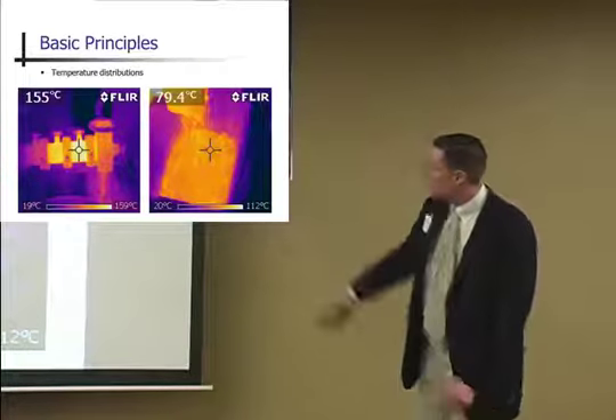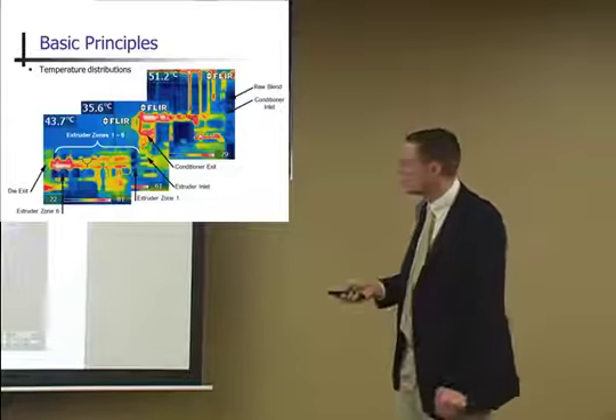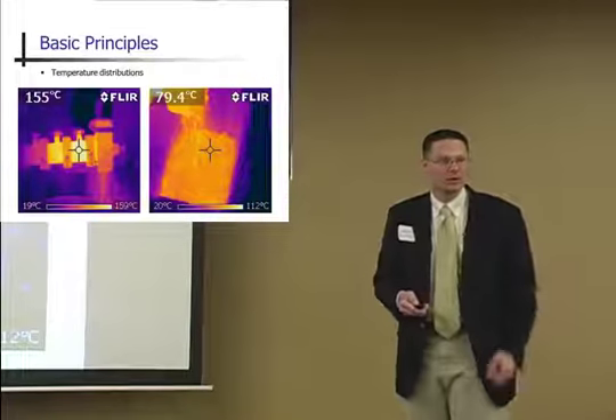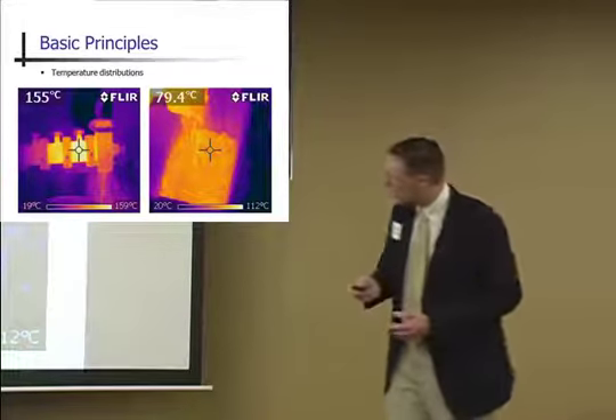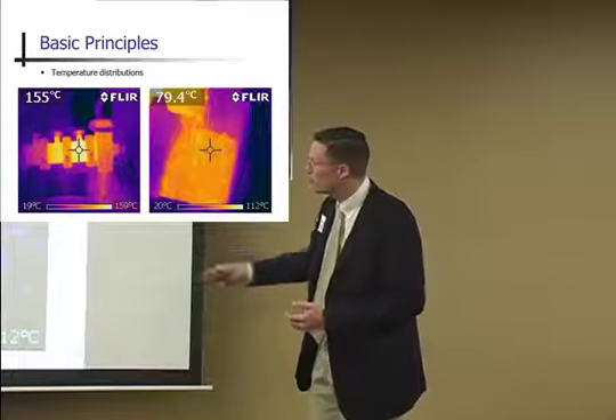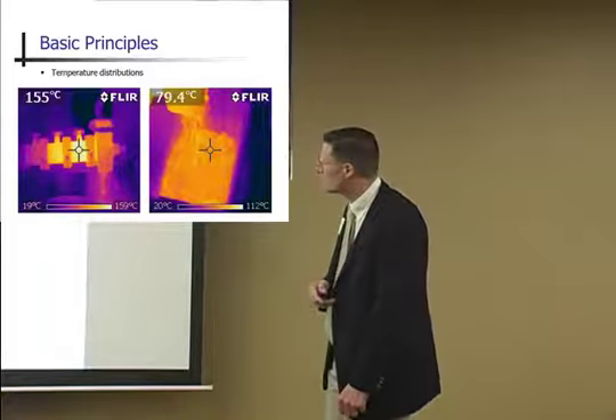So one of the challenges is you don't have a lot of control here, and so if you get high temperatures, your pellet quality is going to decline. And so this type of a system where you can actually control the temperature and the moisture gives you better control over your pellet quality than a system like this, where you actually have to add more water prior to dumping the ingredients into the extruder.